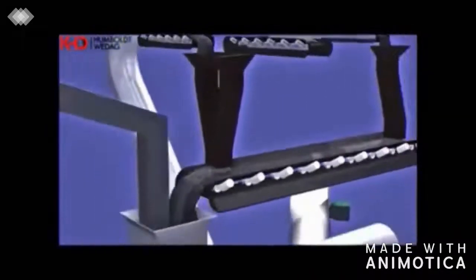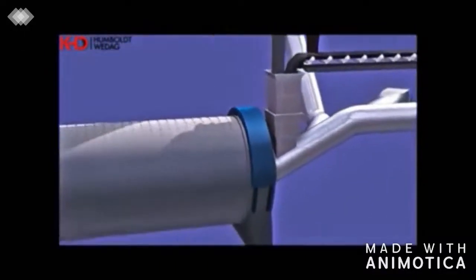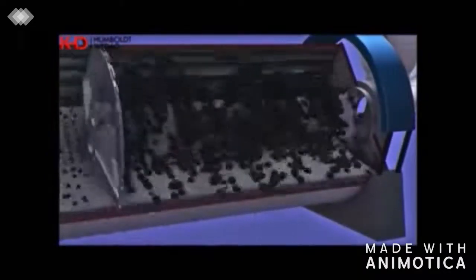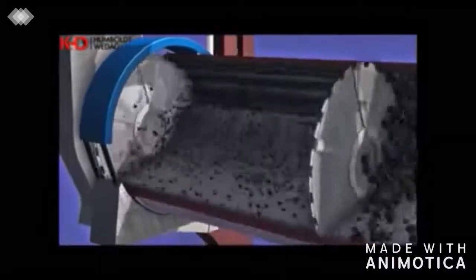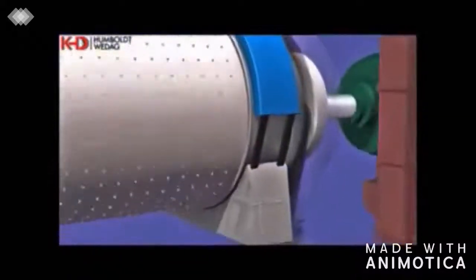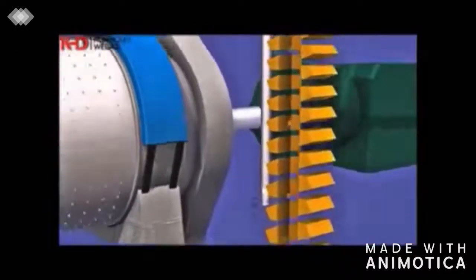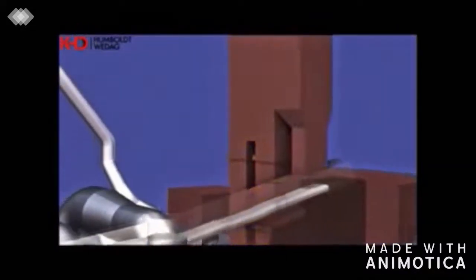Cement grinding is performed in a large ball mill with two mill chambers. In the first chamber, clinker and additives are ground by large diameter grinding balls, which create load impact. The pre-ground material passes through a diaphragm and its finish grinding is performed in the longer second chamber by means of smaller diameter grinding balls, which perform mechanical abrasion. A bucket elevator and air slides then feed the ground product into a dynamic separator.